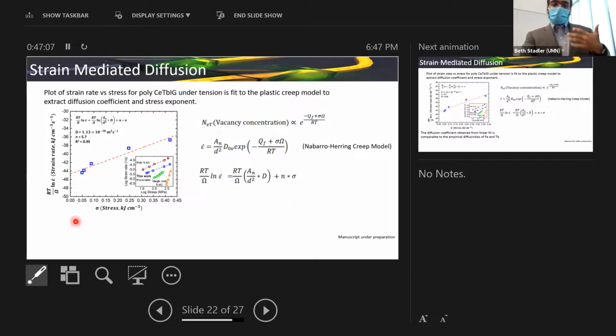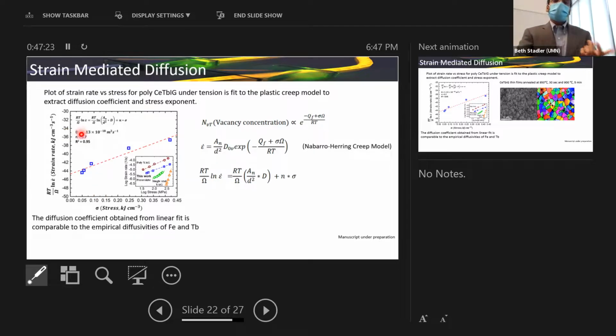When we take our data and fit it with this linear form of the Nabarro-Herring model, we see that it fits quite well with a very high R-squared value, and we also get a diffusivity value from that fitting. The first thing we do is compare this diffusion coefficient, and we see that it largely relates to the empirical diffusivities of iron and terbium, which tells us that iron and terbium is actually driving this process.